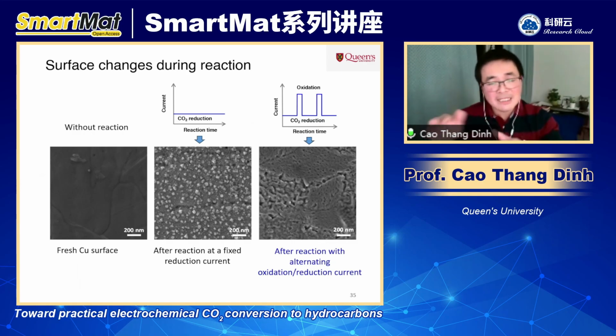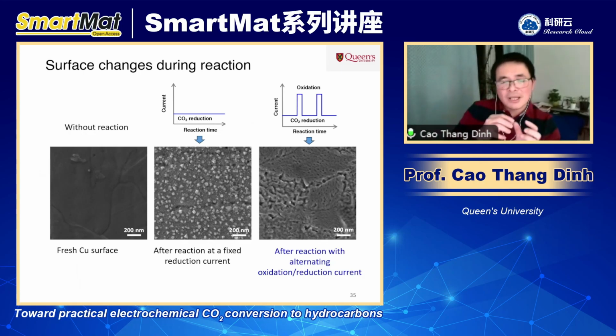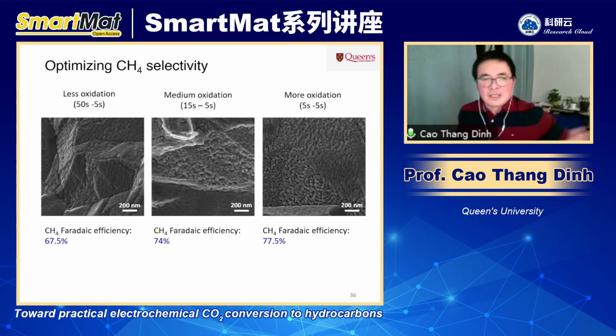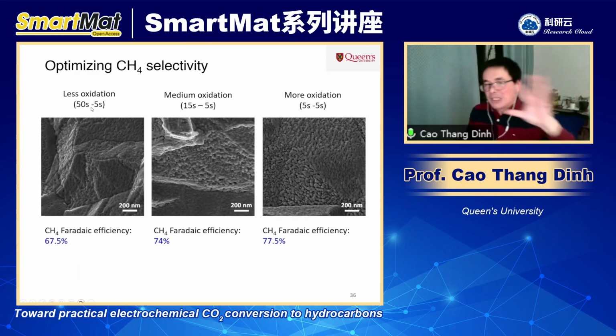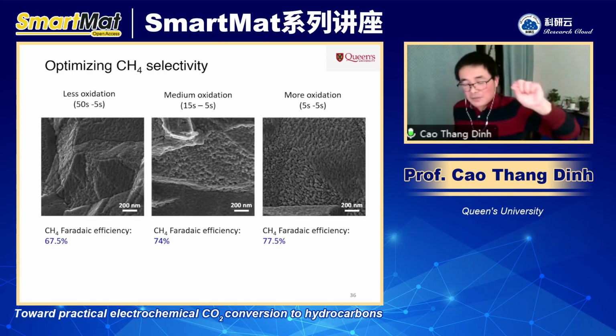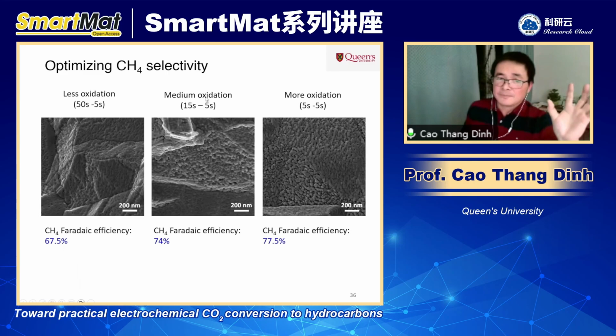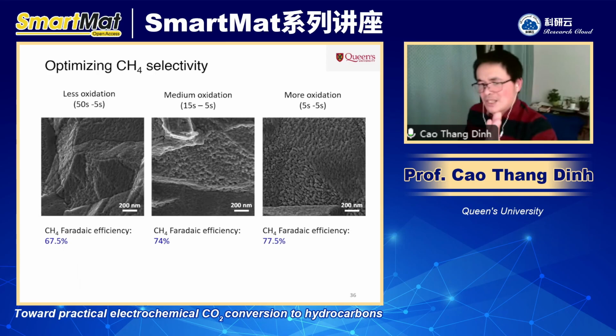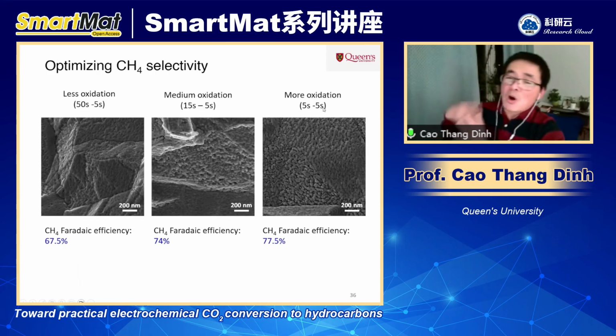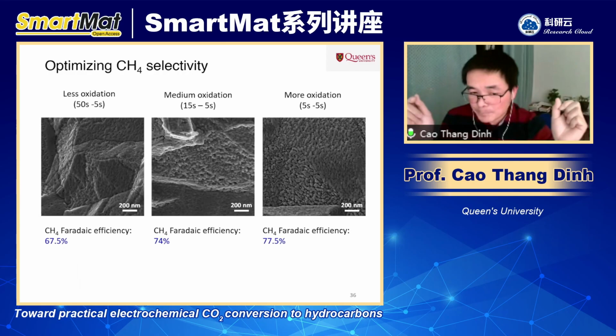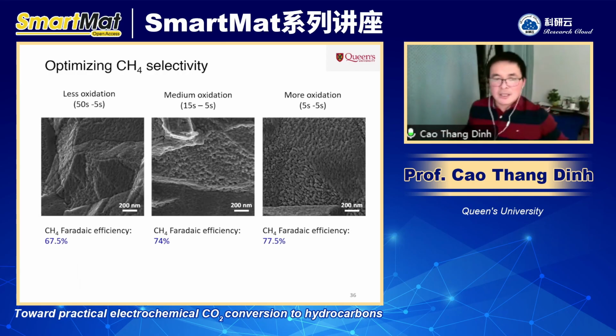And if that is the case, then we can tune the condition so that we can change the surface of the copper, right? And that's exactly what we did, by applying different oxidation reduction conditions. So less oxidation means you have a very long reduction, and then you fix the oxidation at 5 seconds. Medium is 15 seconds of reduction and then 5 seconds of oxidation. And the last one is more oxidation, half of the time. Much different in current though, right? So now you see that you have different surfaces.